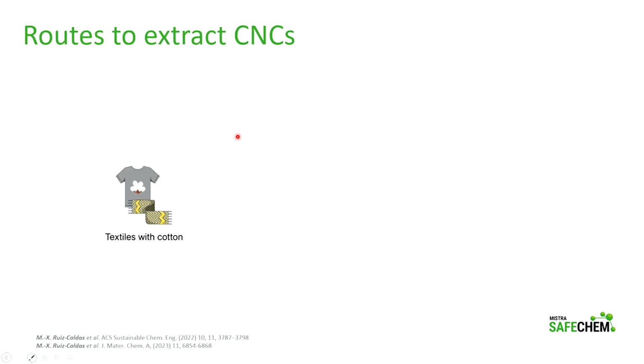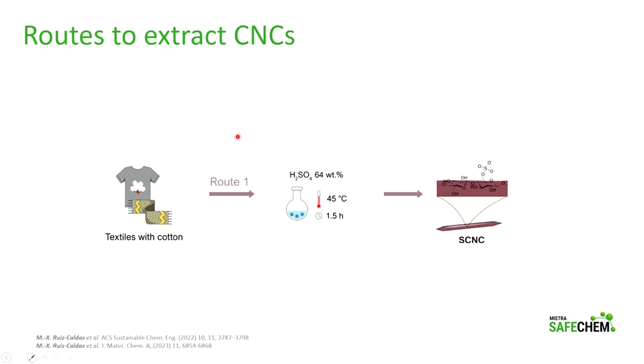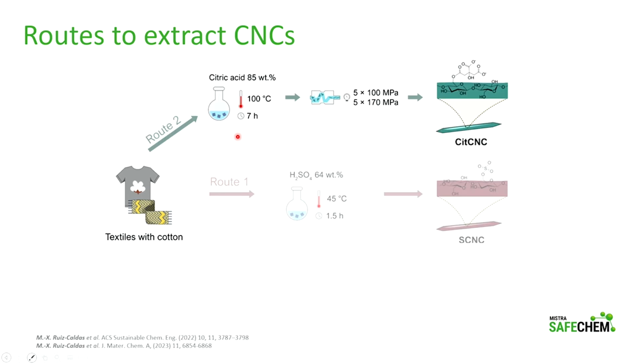So here I'm just going to give a very quick detail of how these routes are done. We start with textiles with cotton, and then through a sulfuric acid hydrolysis, this will be like the scissors that I showed in the picture before, that will help us to isolate these rod-type particles, and we also will have a surface charge that helps to give some extra properties such as colloidal stability. We also try different routes. We used a chemical process to give the colloidal stability, and here with a mechanical process, we made the scissoring in order to isolate these rods, but instead of having sulfate half ester groups, we will have these citrate groups that will give us other types of applications.